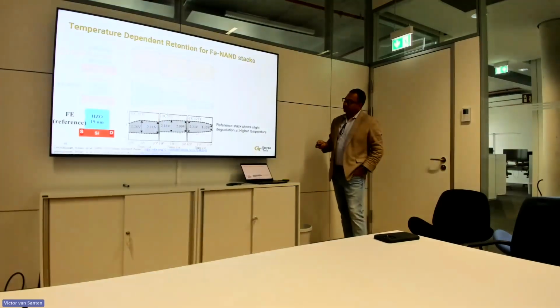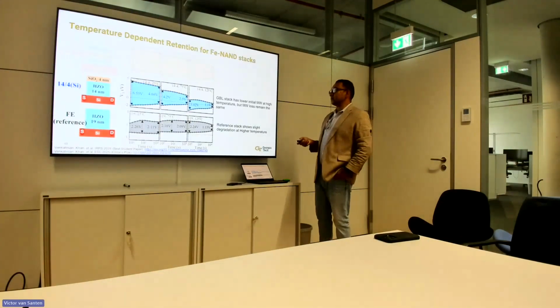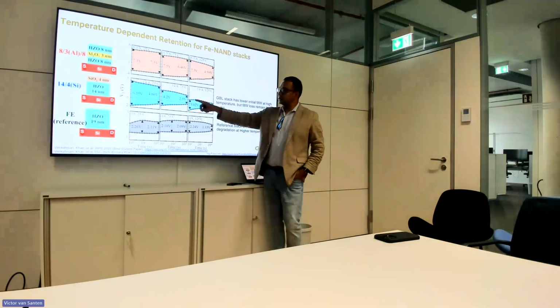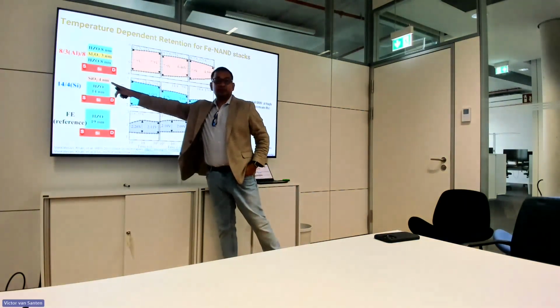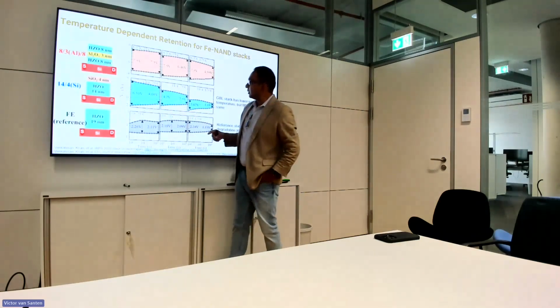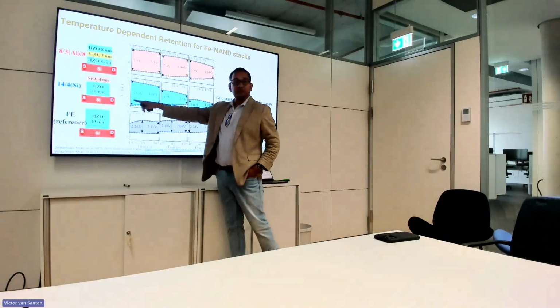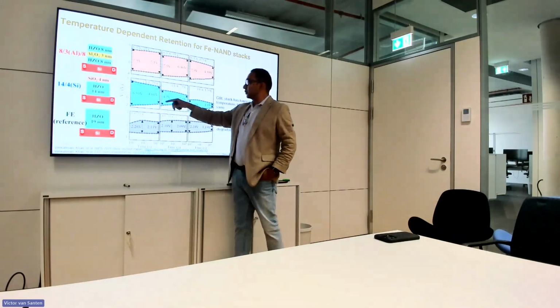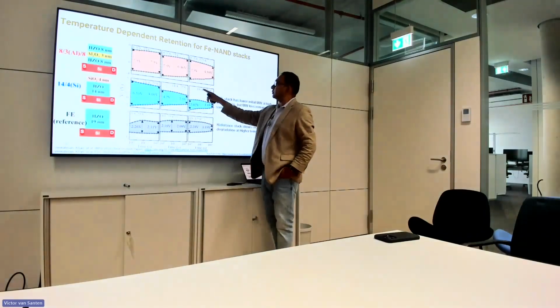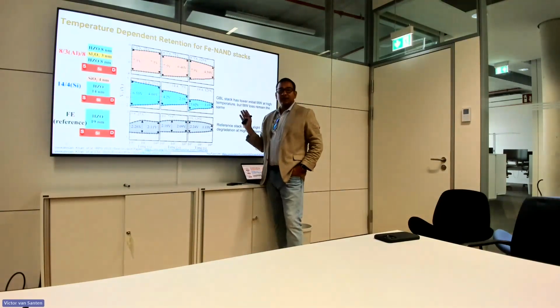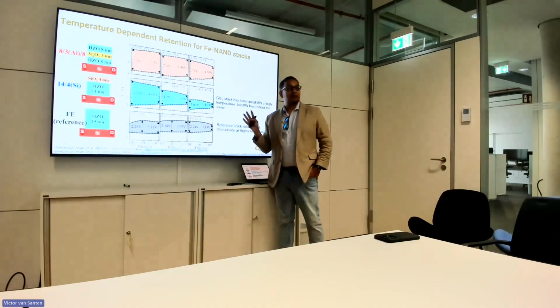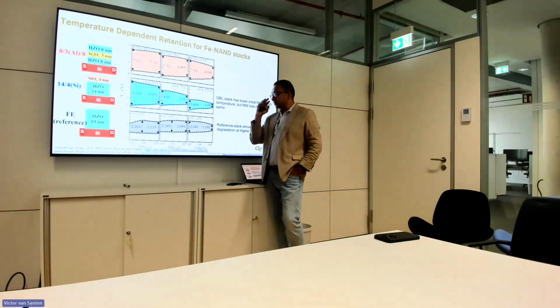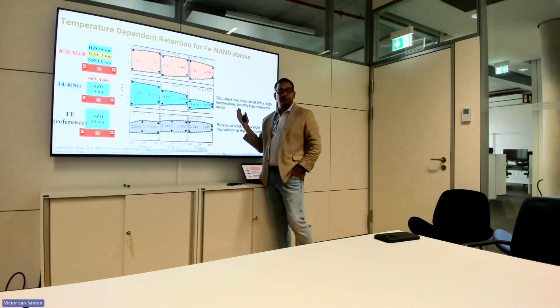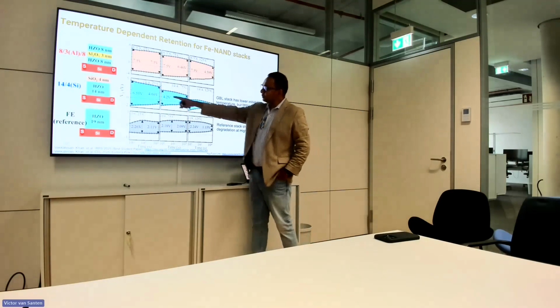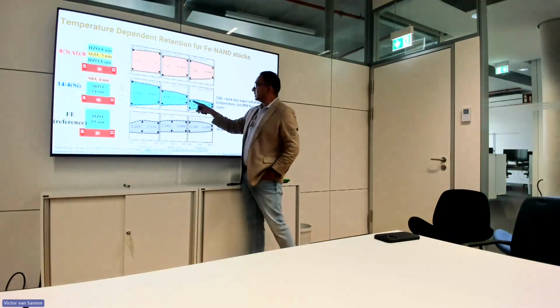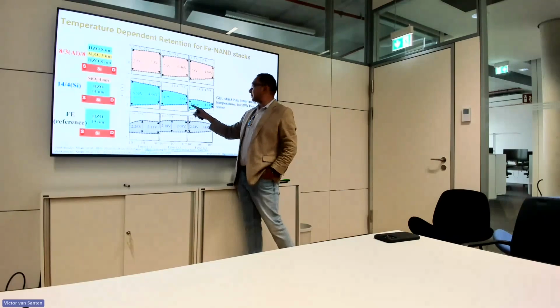But what is quite interesting is that if I put the layer over here, either aluminum oxide or silicon dioxide, it shows quite a large memory window at the beginning, but the retention is poor, meaning that you can see it goes down. And if you go to 125C, why 125C? 125C or 115C is more like a higher temperature limit where any device, any chip needs to be qualified for a certain amount of time. So when you put the dielectric layer on top, you can see that the memory window goes down significantly and the retention is poor.